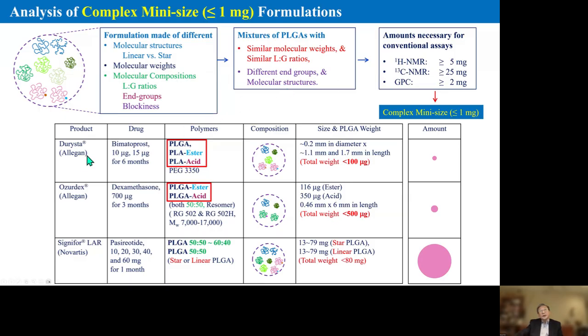Now, in ophthalmic products, Durysta and Ozurdex, in terms of the composition, is unknown, because Durysta contains PLGA, PLA ester, PLA acid. We don't have any further information. Ozurdex contains PLGA ester and PLGA acid. Fortunately, the manufacturer presented information that they use a Resomer, both LG ratio 50-50, and molecular weight is 7,000 to 17,000. No more information. So the question here is whether we can separate PLGA based on this acid end group or ester end group. So we'll talk about that first.